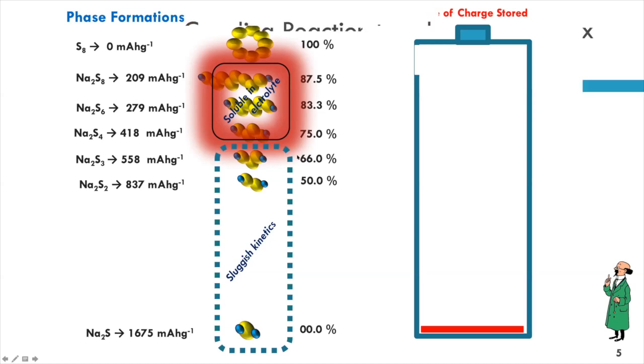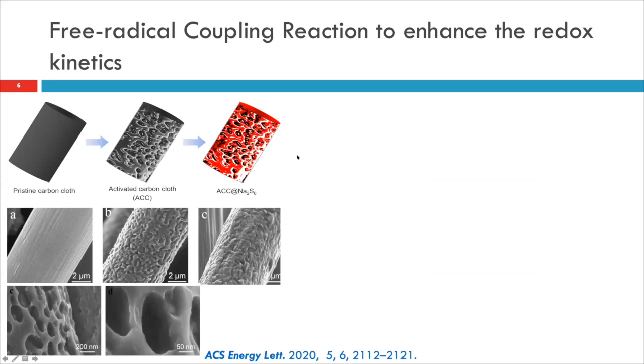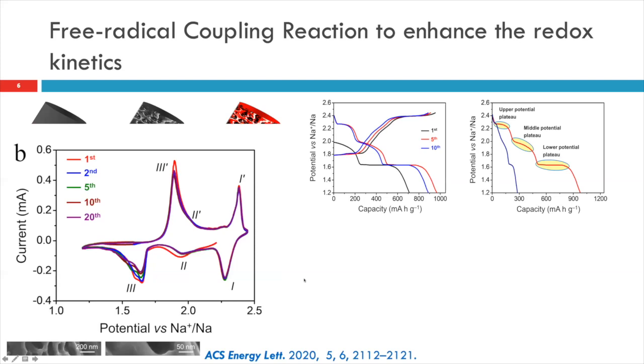So here I will show you one of the new things we observed during these studies. We took a pristine carbon cloth, and in a very specialized way we corroded this surface. This is a huge corrosion we have done, very controlled, and made it highly porous. You can see the holes are created very high. So here we made this current collector a host for polysulfide. That was our interest. And when you look at the cyclic performance,